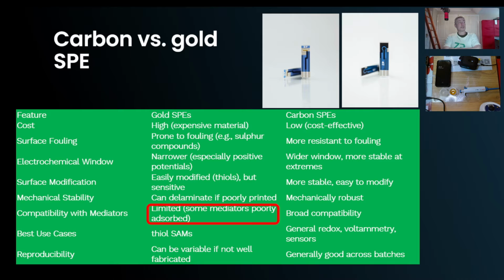This is a true statement, that when you try to modify gold electrodes with mediators, I found those to be quite difficult. Sometimes you're doing voltammetry, so the mediator is being put down by electrochemical deposition or electrochemical polymerization. It doesn't have a great adherence to gold because it can tend to be a bit smooth, whereas you will get good adherence or compatibility with mediators when it comes to carbon. Many mediators are organic in nature, so they have a tendency to pi stack with carbon surfaces. Best use case scenario for gold is self-assembled monolayers.